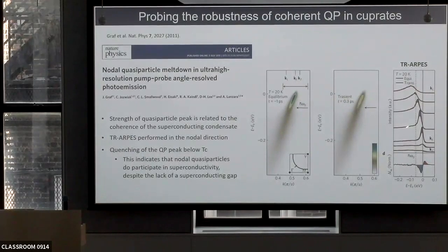And if you look at the detail of a spectrum taken at a given momentum here, as a function of energy, you can see, for instance, that between the equilibrium data in black and the red one, the transient data, there is a difference. The difference is concentrated on the peak. The peak is what we would call the quasi-particle, and the area under that peak is what we usually would call the quasi-particle strength. And so what you're seeing here is that by coming in with a pump, you basically suppress the coherence of those quasi-particles, or at least this is the interpretation. But certainly you're doing something, now you're not just populating states above EF, you're doing something to the spectral function itself.